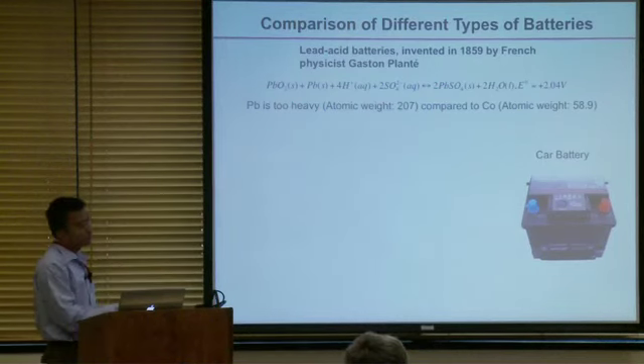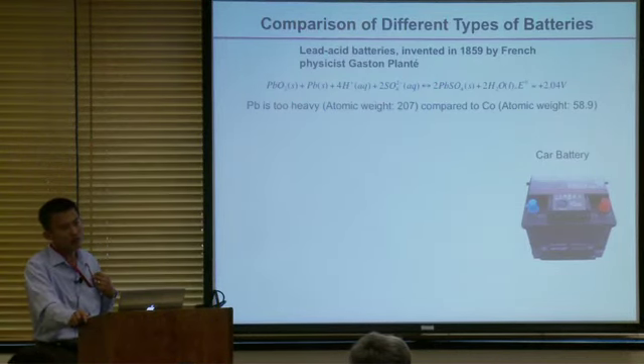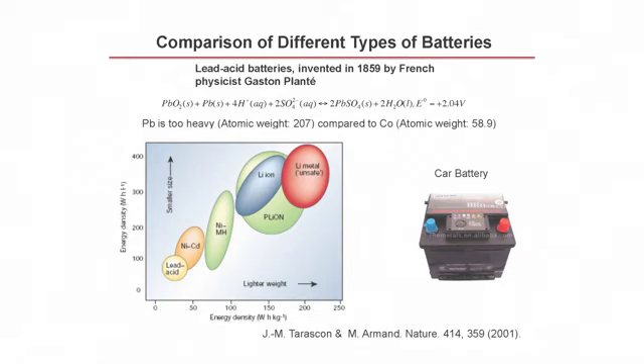So looking at the lead-acid battery, that's really the workhorse for a long time for the car. This is the reaction for the whole battery. You have theoretically 2 volts per cell, and coming back to the energy density, you can calculate. Lead is too heavy, atomic weight is 207. Cobalt in the lithium-ion battery is only 59. There's a big difference. At the end, it comes back to the energy density and specific energy. Lead-acid is right here in terms of energy per unit weight, and this is a lithium-ion battery, which is a lot higher. So it's a lot more attractive compared to other technology.